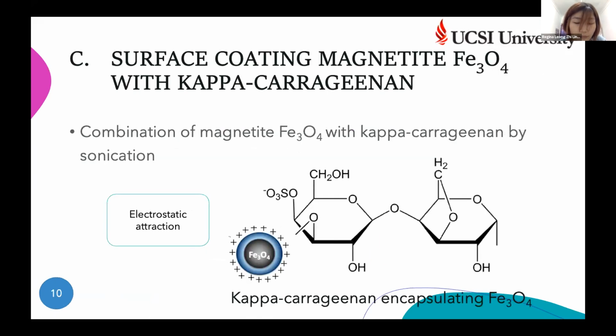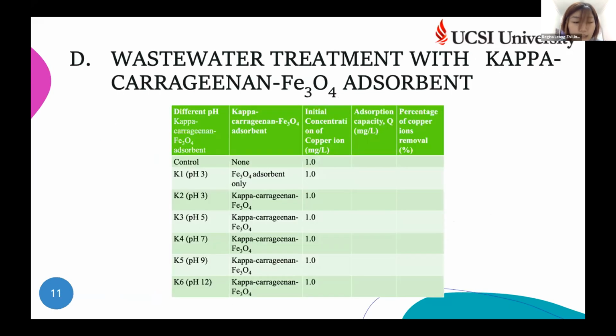Then surface coating of magnetite iron oxide with Kappa-carrageenan will be done by sonication. So the Kappa-carrageenan will encapsulate the iron oxide by electrostatic attraction. Lastly, the magnetite Kappa-carrageenan iron oxide adsorbent will be used in wastewater treatment to determine the capability in removing copper ion. So we will set up the experiment design as shown in the table, with different pH of Kappa-carrageenan iron oxide adsorbent, and measure the adsorption capacity as well as the percentage of copper ion removal.